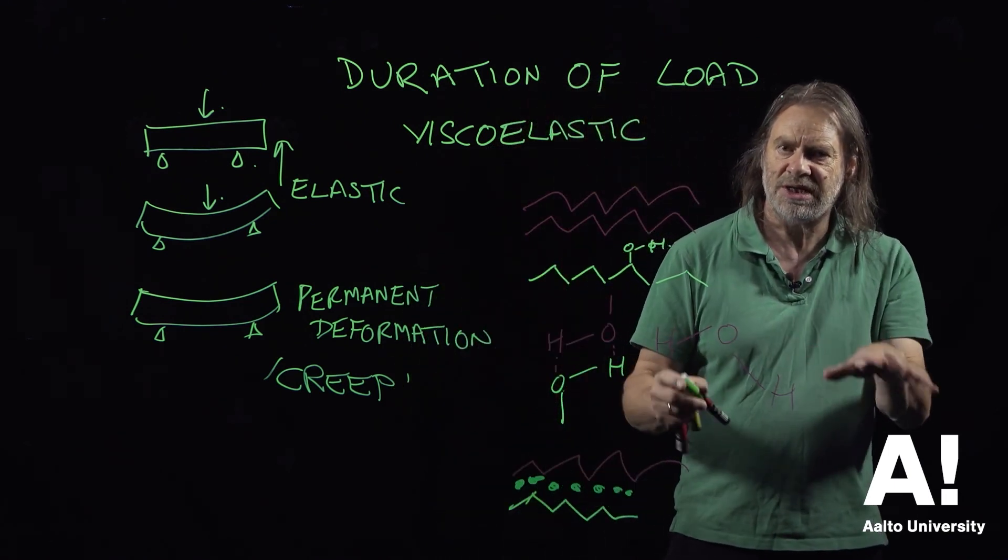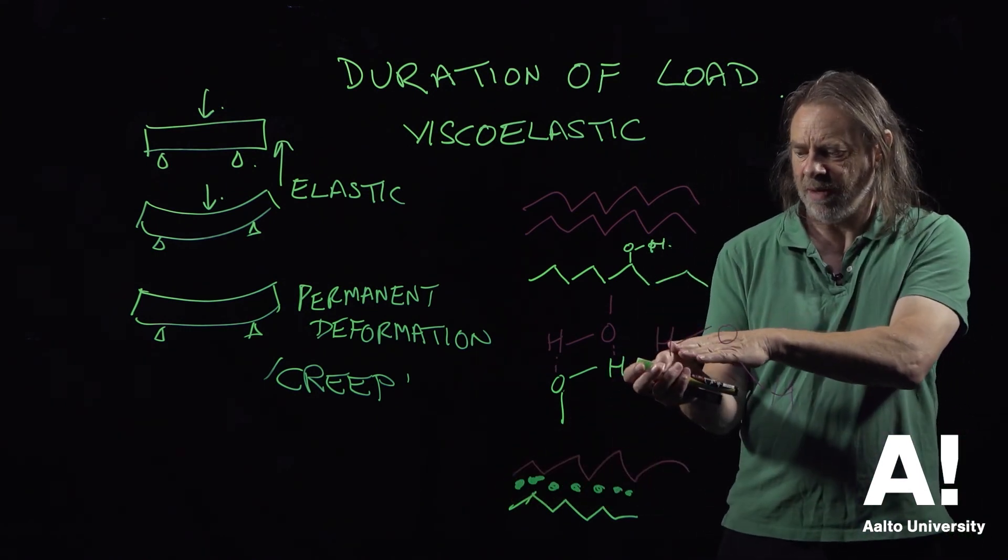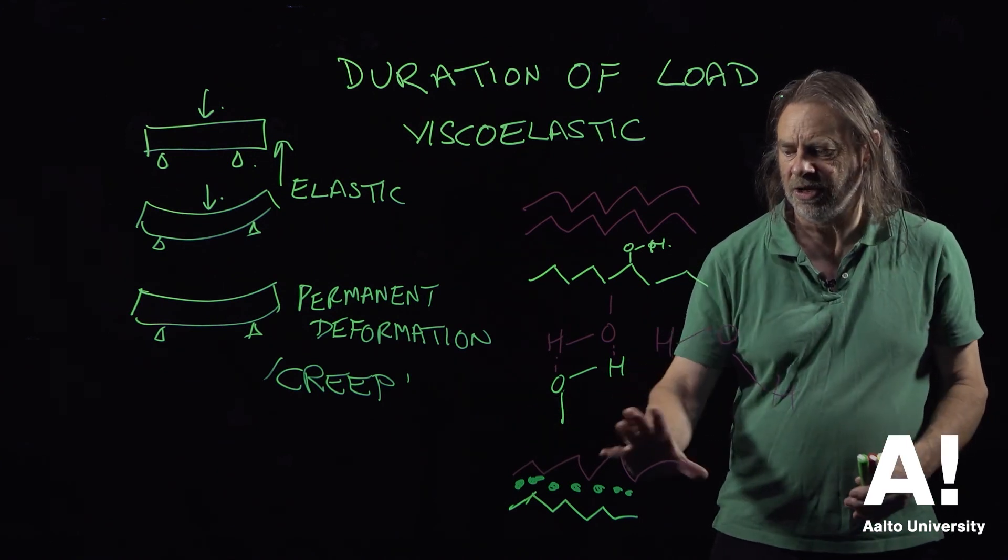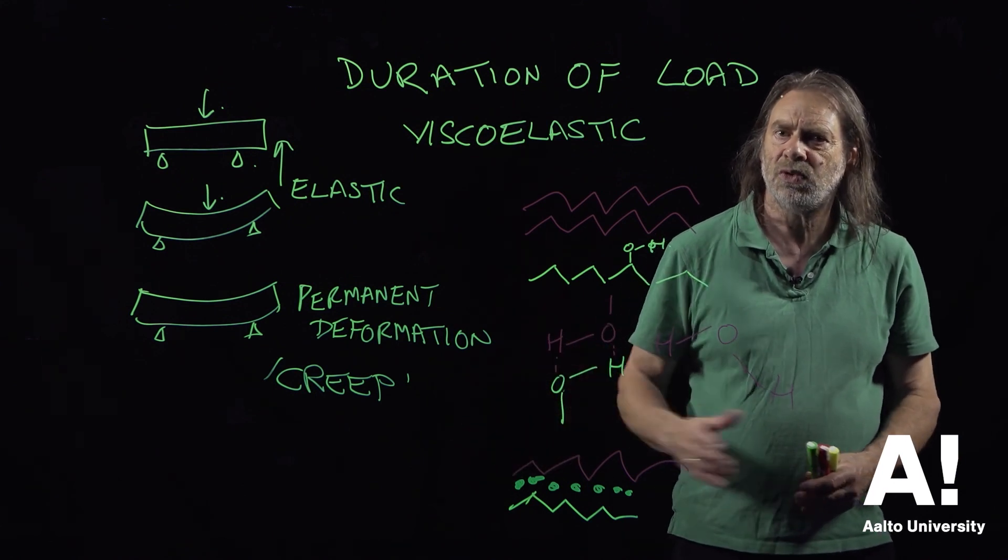So we get this what's called a stick-slip mechanism. So if we're applying a load for a long period of time we will get permanent movement of these regions and that explains the creep. So you don't get it with dry wood, you need water to be present.